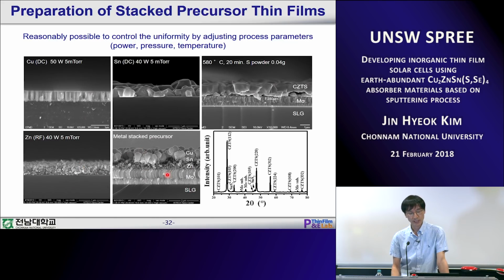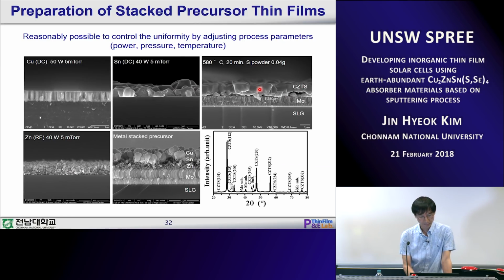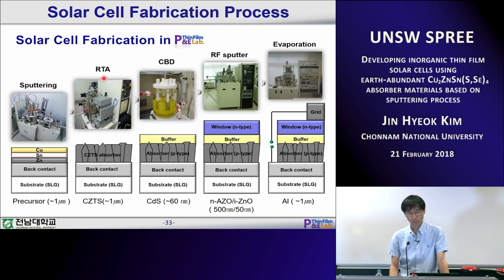So we have this stacked triple layer, and after the sulfo-selenization process, we could have this CZTS absorber material. After making this absorber material, that means after this RTP, rapid thermal annealing or rapid thermal processing, we use both words, we have to put the buffer layer using the chemical bath deposition process, and then we have to put the window layer. And then we have to put the top electrode material. After this, we can make a cell.